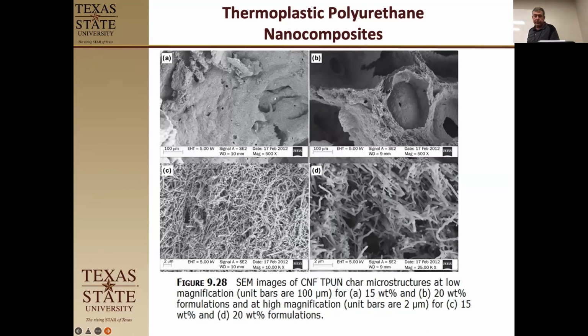And then this is where we have looked at the carbon nanofibers. The carbon nanofibers behaved a little differently because they'd already been pyrolyzed once, so they are not going to burn again. But look at the mat type structure. As you go with just a little bit here in the higher mag, you have that surface texture. But then you look down here and you see the network of the carbon nanotubes that are holding up the system, the char layer. So that char layer is getting thicker with non-pyrolyzed material. So again, it should have done better, but it's just pumping too much heat into the base right here.